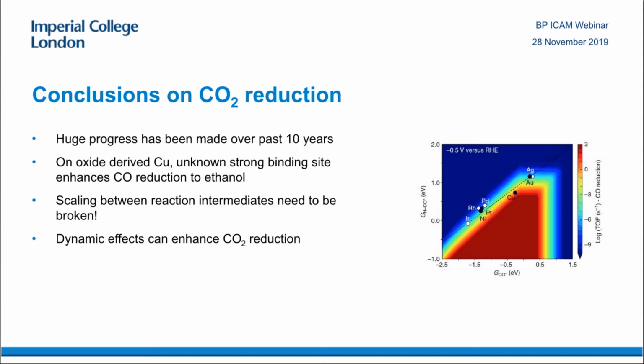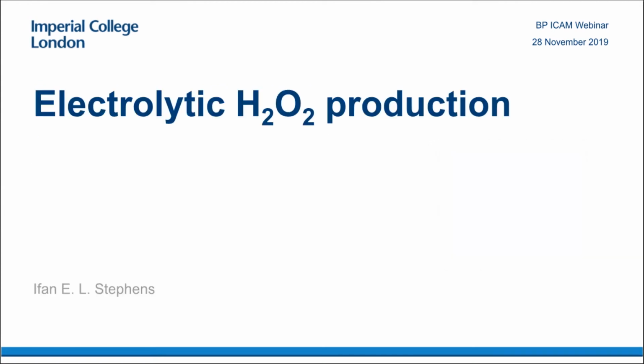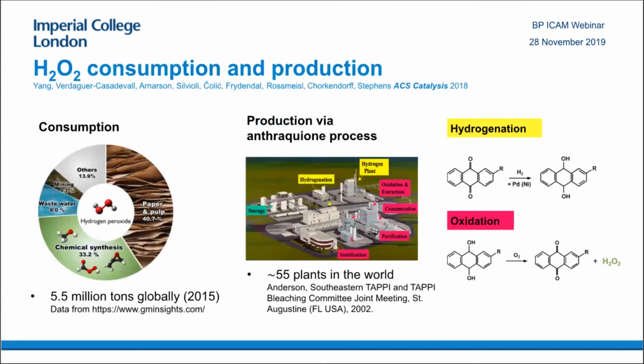But in summary, there's been huge progress made over the past 10 years. On oxide-derived copper, we found it was one of the most promising catalysts. We found an unknown but very strong binding site can enhance CO reduction to ethanol. To really go even further, we need to break the scaling between reaction intermediates, so we need to break this linear scaling. One effect that might be able to do that is to tailor the reaction dynamically. That's something I want to explore in more detail. Finally, I'd like to go very quickly to hydrogen peroxide production, if I may.